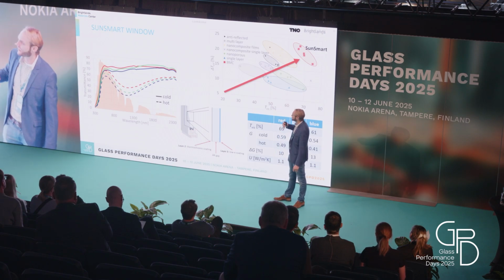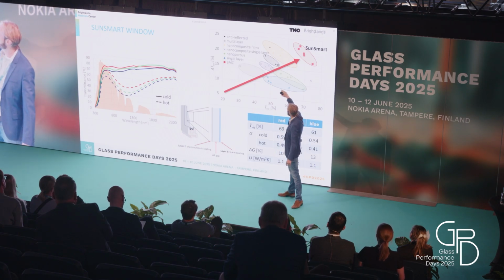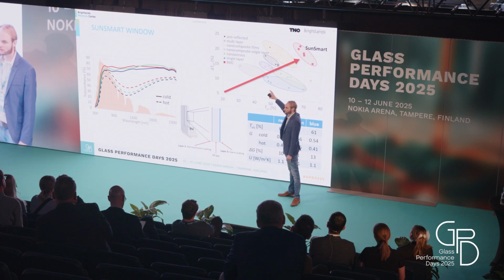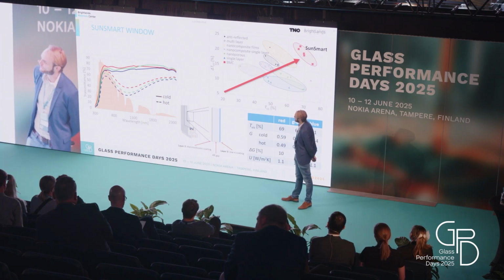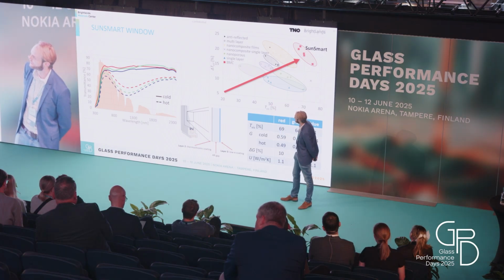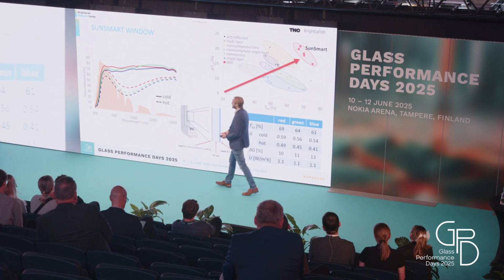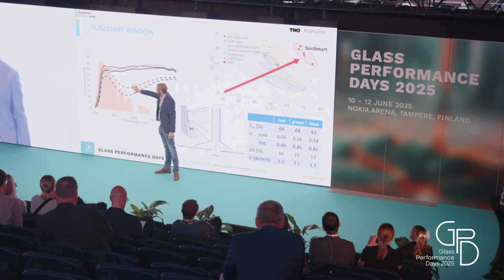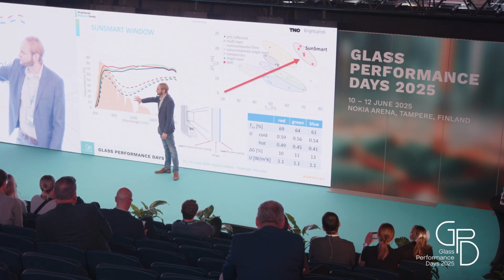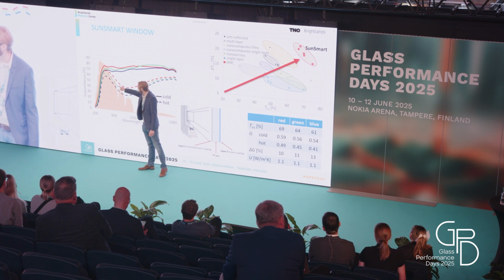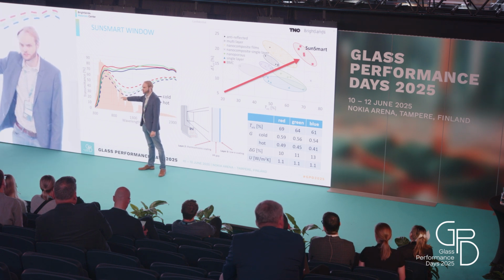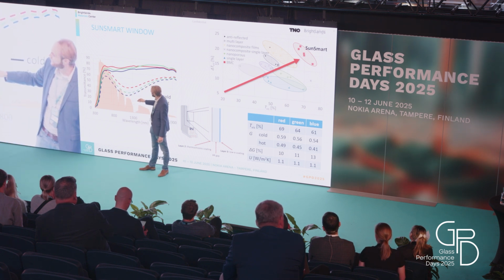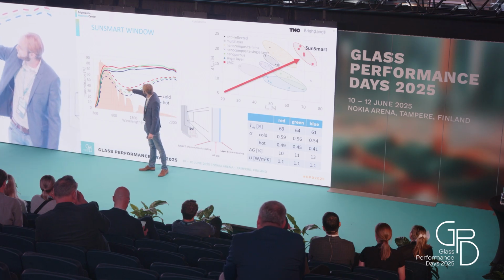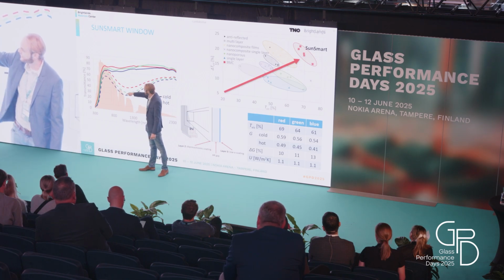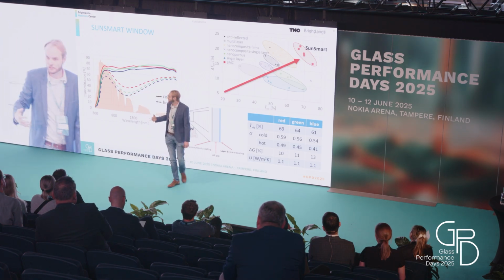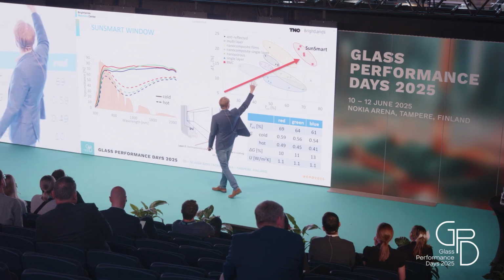But if you add so much functional material, then usually the overall transparency goes down. And that's something that we have optimized in the last years by especially focusing on this part of the solar spectrum between 800 and 1400 nanometers. And you see this is the part where the largest part of the infrared transmission of the sun is. And by optimizing the modulation in that range, we can achieve a very high transparency together with a high solar modulation.